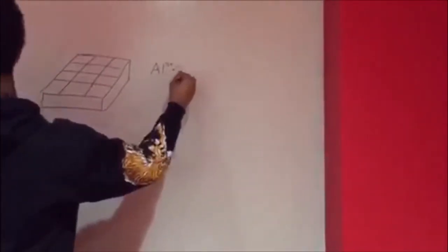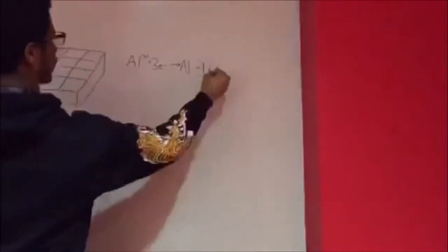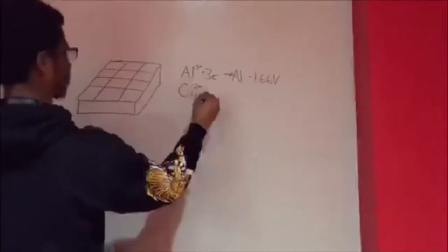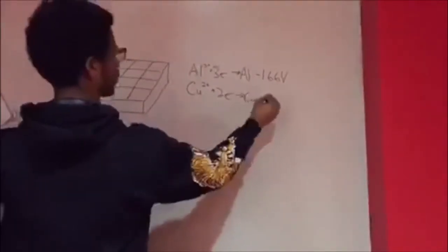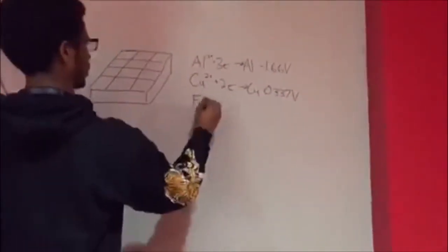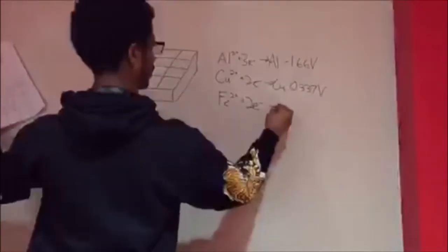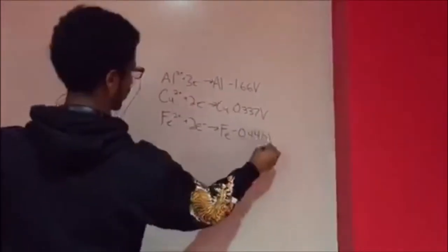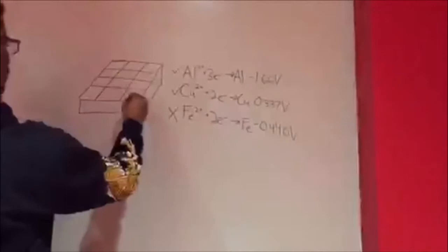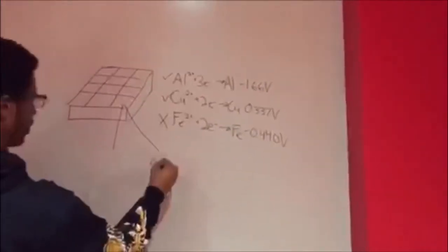Over the course of 2 lab sessions, my team tested different ideas to try and optimize the power of our battery using the resources available to us. As the container for our battery, we had a 12-compartment cell. First decision we had to make was which metal wires, out of our available options, to use as our cathode and anode. With some research, we found that aluminum and copper had the largest difference in their reduction potentials, which would lead to the highest voltage.